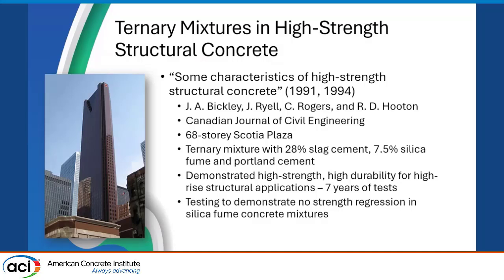Also, Doug's done a lot of work with ternary mixtures of various types: ternary with slag and silica fume, slag and fly ash. Generally, most of them have some type of slag in there. His paper, Some Characteristics of High-Strength Structural Concrete, summarized one of these structures, the 68-story Scotia Plaza building. It had a ternary mixture with 28% slag and 7.5% silica fume, and there was some concern about strength retrogression in silica fume concrete, so he did some testing over 7 years to ensure that was not happening.